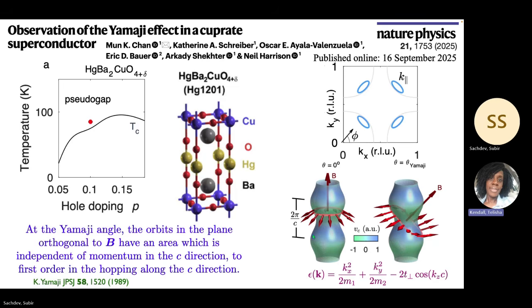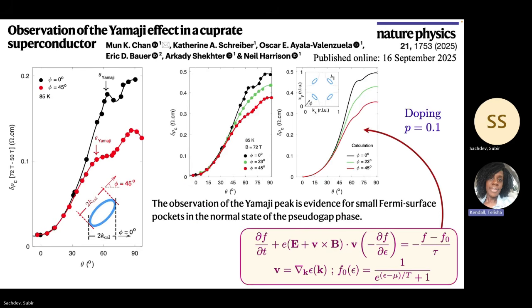Anyway, so they measure as a function of theta and phi, the different values of theta and phi, just the resistance in the third direction. And I see certain peaks which are very characteristic, the Yamaji peaks, from which you can read off the area of the Fermi surface. In fact, this is the calculation from a very simple Boltzmann equation compared to the data as a function of theta for different values of phi, and it all works very beautifully.